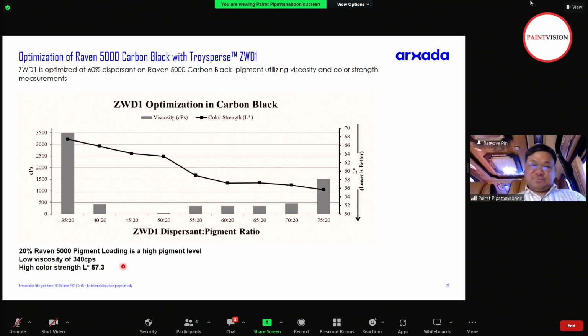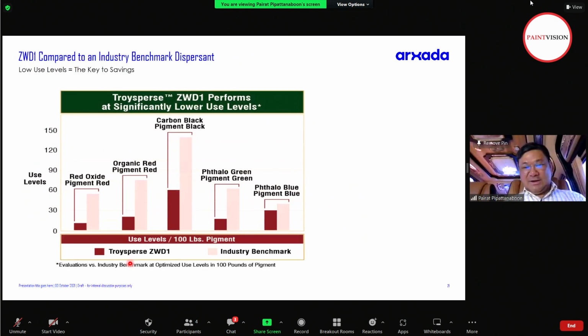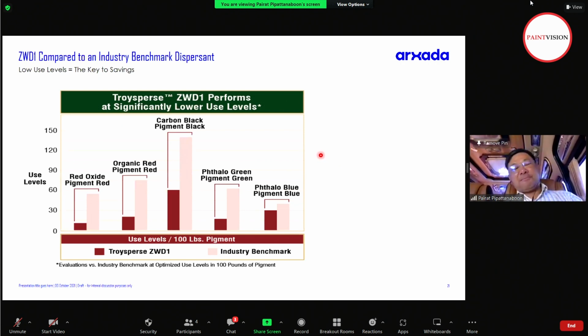after tinting. So we look at two factors. First, the viscosity of the paste should be lowest or low level, so it can be flowable. Second, you get the highest color strength after tinting. Why do you need the lowest or flowable viscosity? Because at a flowable viscosity of pigment paste, you are able to load more pigment into your formulation. That is the objective of the lowest viscosity of pigment paste that we need to calculate.